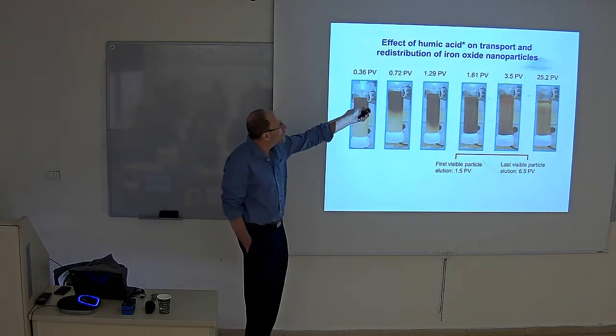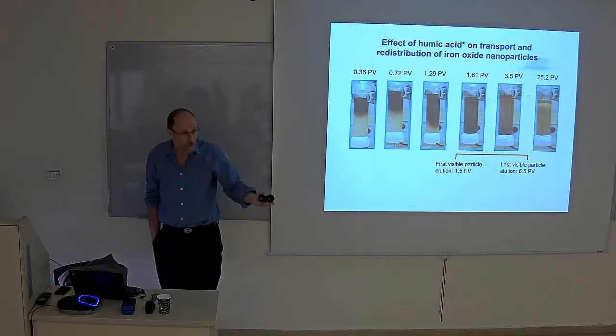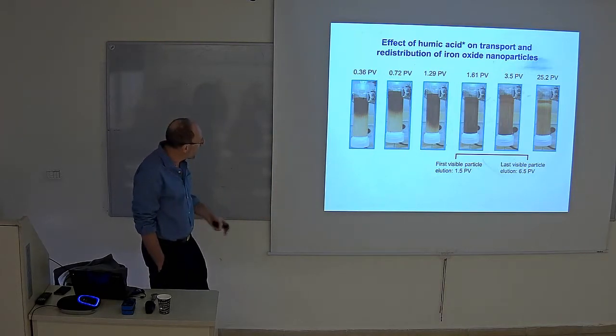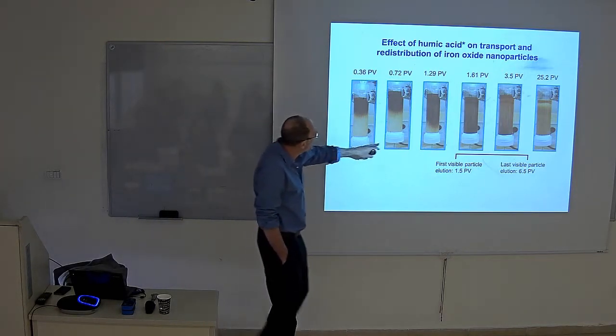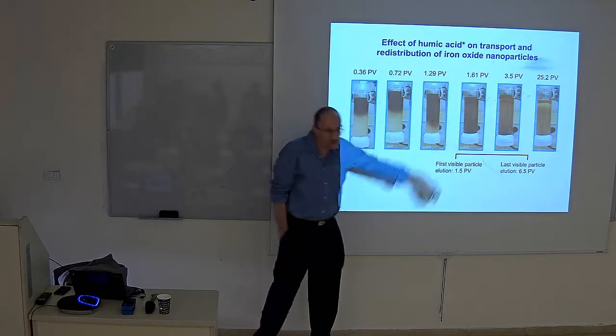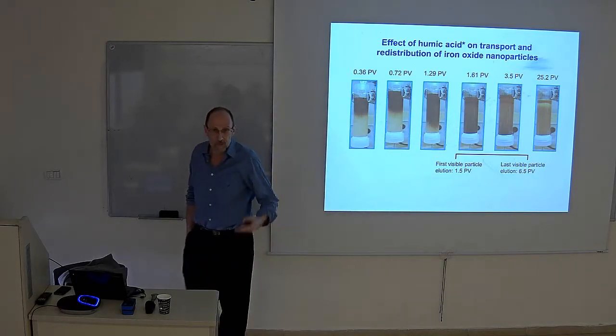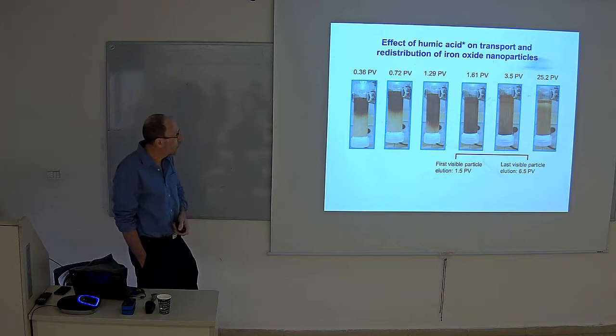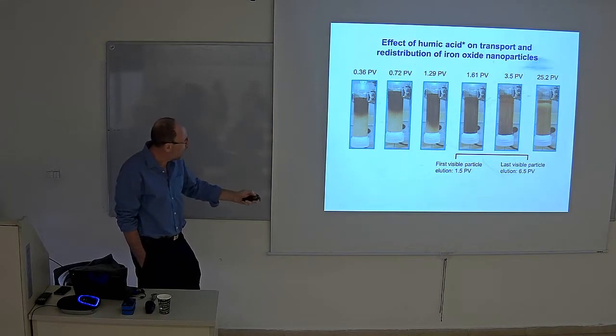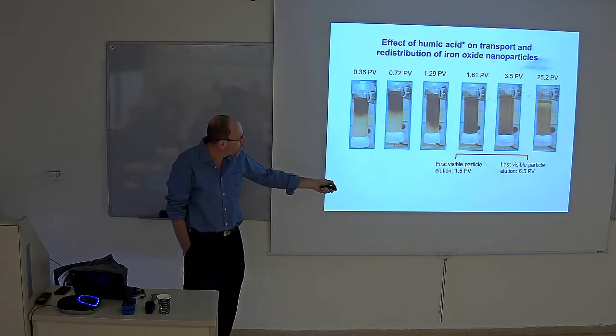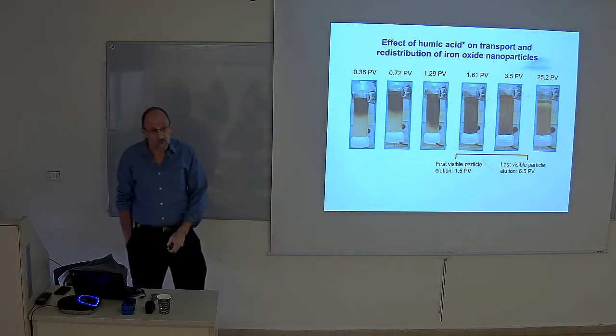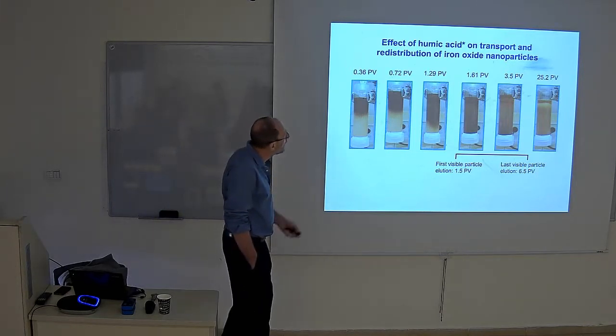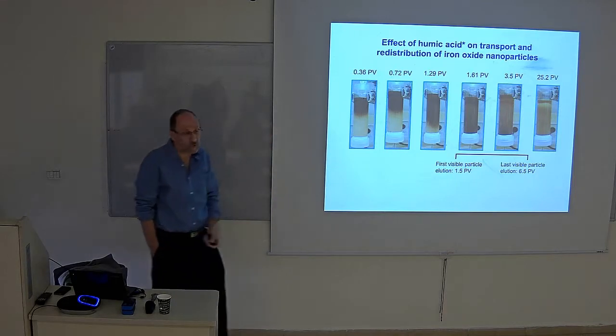So then you say, just a moment, add humic acid. We know there's a lot of humic acid in the soil. What effect does that have on the glass beads? With humic acid, within a couple of pore volumes, it's moved through already. So, in other words, it becomes very, very mobile. And after 6 or so pore volumes, essentially the column was cleaned out. So humic acid and glass beads moves very quickly. That was with iron oxide particles.